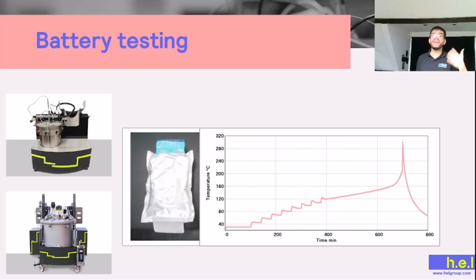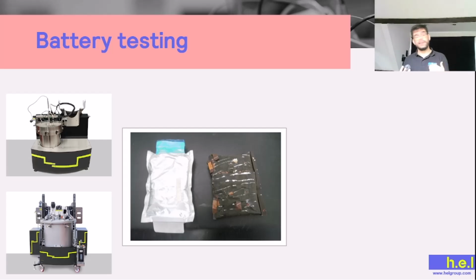But then, around 120 degrees, we're going to find that this is not the case. Instead of stabilizing, we're going to have an increase in the temperature. We're going to have self-heating processes, and this is when the battery gets into thermal runaway. And we can see that the temperature in the battery can reach very high values, like 290 degrees. What happens with the battery when it's exposed to these conditions is that originally it was the picture that we can see on the left hand side of the graph, but at the end of the experiment it's going to look like that, which is not that different from what we could see here.